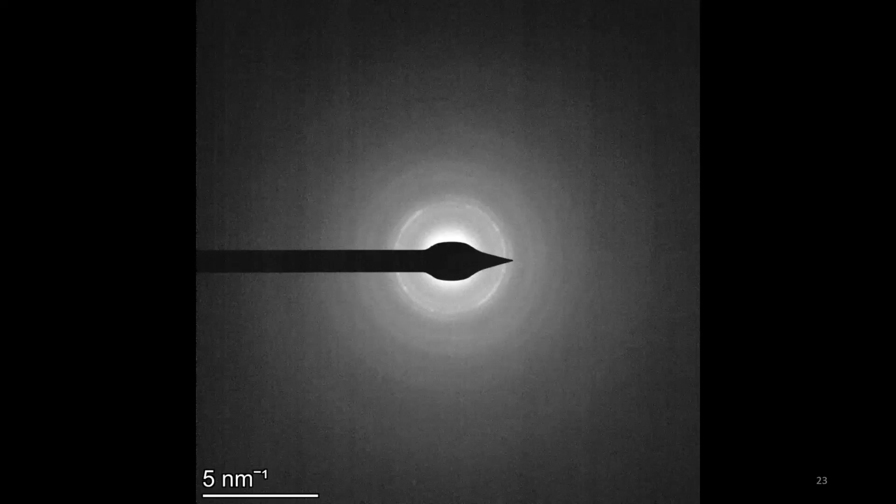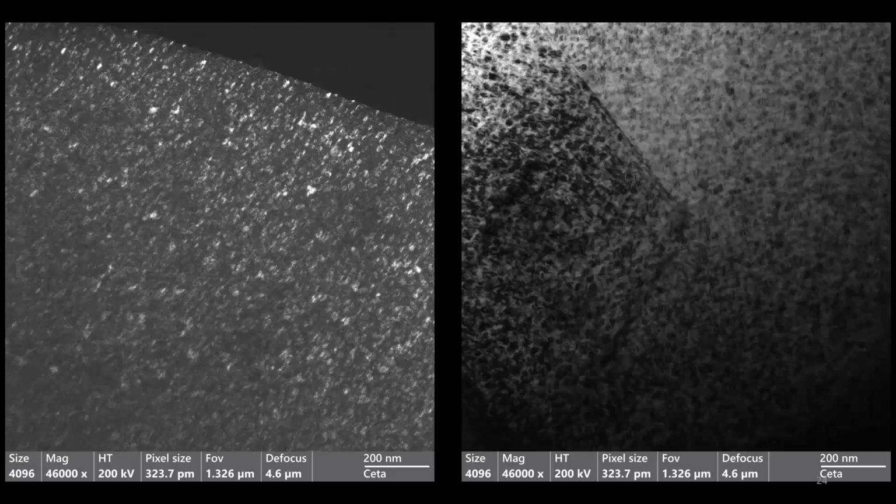Here's another one that's kind of exciting. So Dr. Yakuman has had me hunting for carbides for the longest time, and they're really, really elusive creatures. But I was able to get this diffraction pattern the other day, and these rings are just about where they should be. So they're there. The trick is I had a really, really low dose rate here. And so we're working on getting everything set up on the microscope to be able to give it a low enough dose rate not to damage the carbides and be able to image them at the same time. We're going to get there. It's just time.